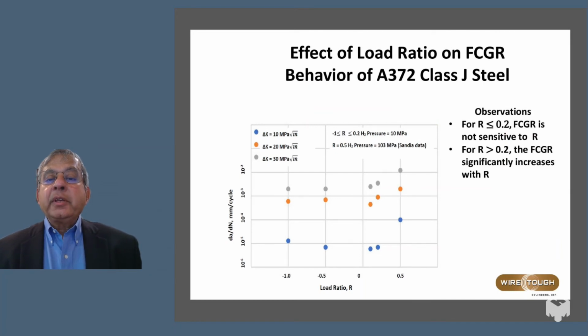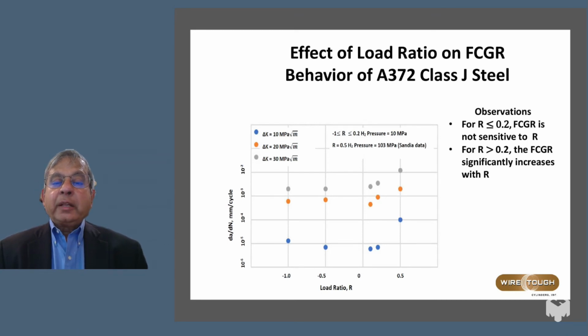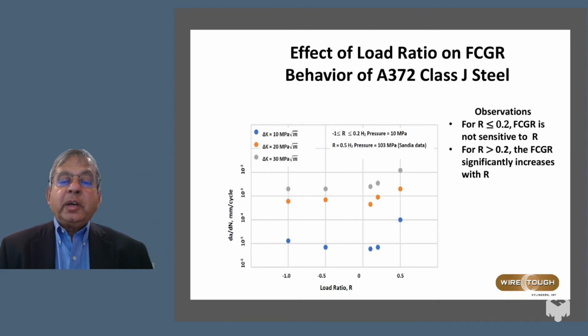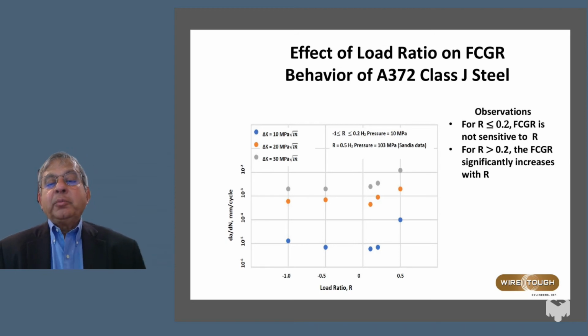Then this is the effect of load ratio, and we can plot the effect of load ratio at different values of delta K. You can see that between minus 1 and about 0.2, there is very little effect of load ratio. But once you go beyond R of 0.2, you do see an increasing effect of load ratio. So that is something that we have to keep in mind when we do our testing, and also when we use test data in application.